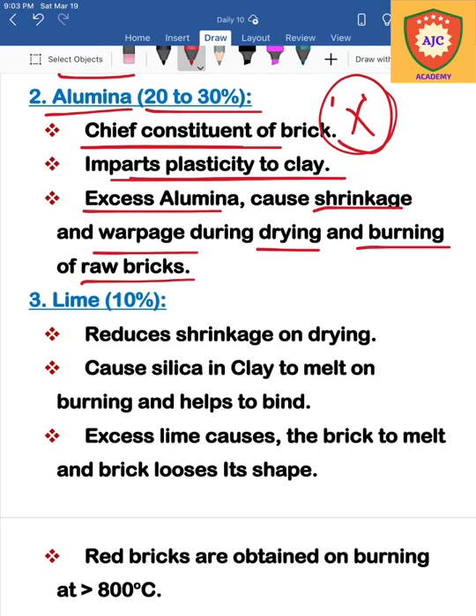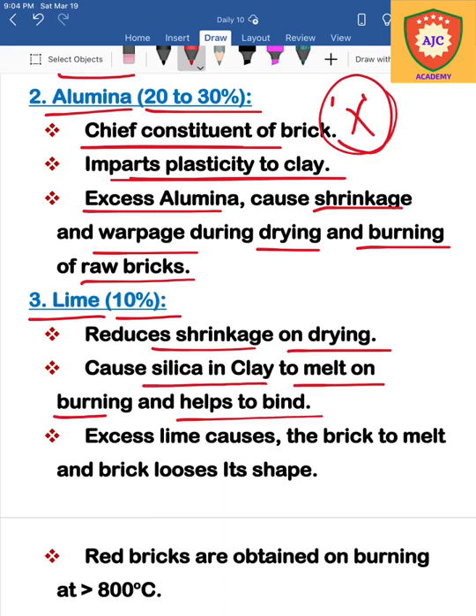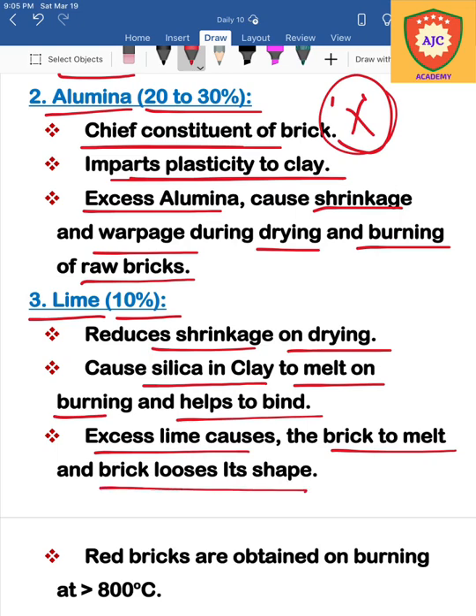The next ingredient is lime, which is present at around 10 percent. Lime aids in the drying process. However, excess lime is a drawback — it causes the silica to melt and form a glass-like material in the clay, causing the brick to lose its shape during manufacturing.